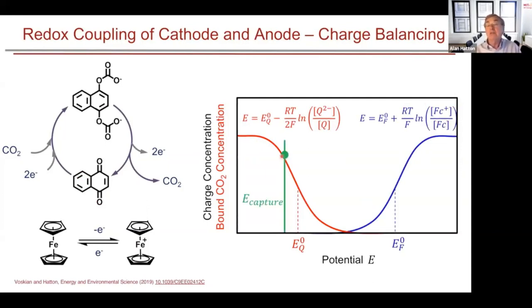So if we apply a potential here and we capture CO2, the amount of CO2 bound would be given by this quantity at this point. But because we need to have a charge balance, the electrons have to come from somewhere to give us that charge concentration. We have the same charge concentration on the ferrocene electrodes as well. And this then gives us the capture potential. When we actually capture, the cell voltage, when you apply a voltage across the two electrodes, is what you would need to get this level of charge transfer and CO2 binding to the electrodes. Then when you want to release, of course, we can apply a different voltage. And this would be the voltage that we would require to give us a bound concentration at about this level. So the total concentration swing, you might say, in terms of the CO2 that's captured and released is given by the difference between these two points over here.